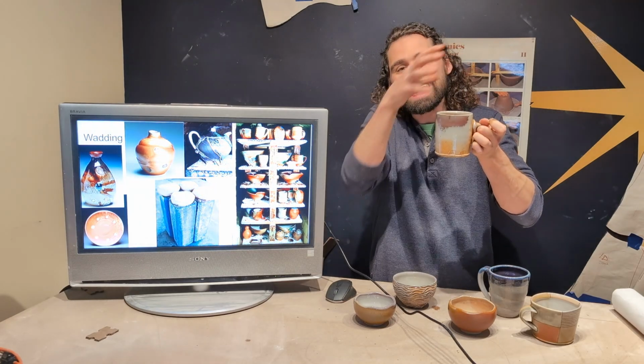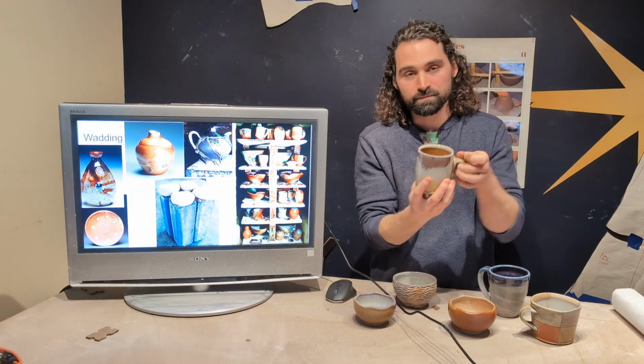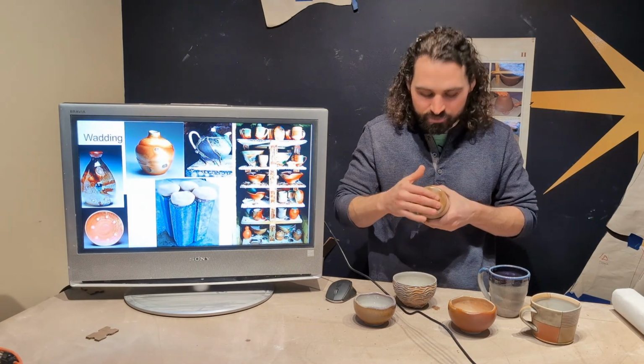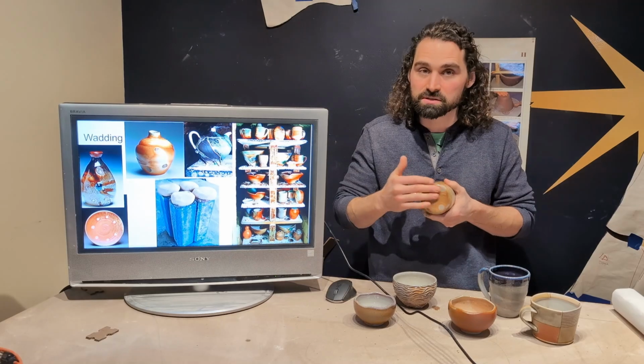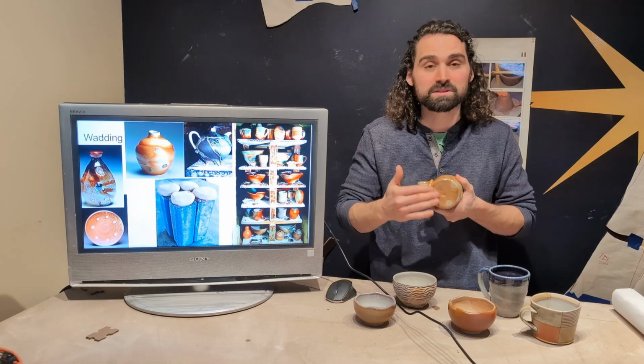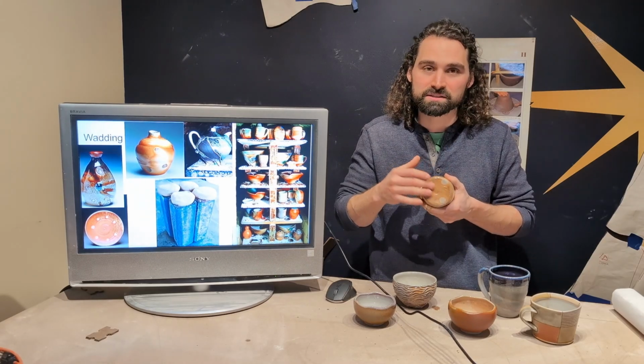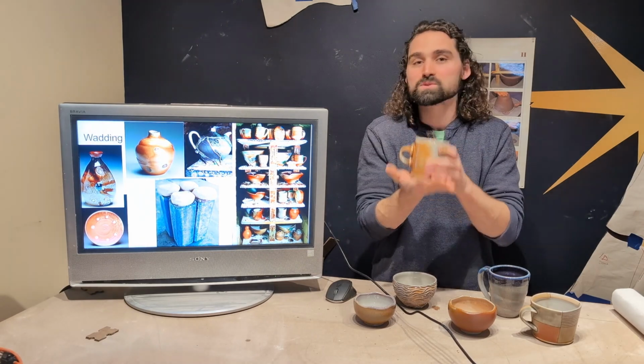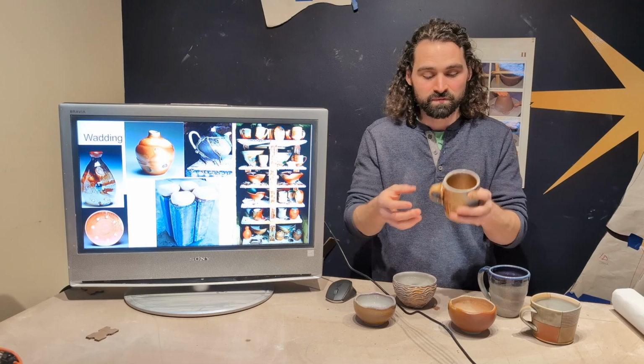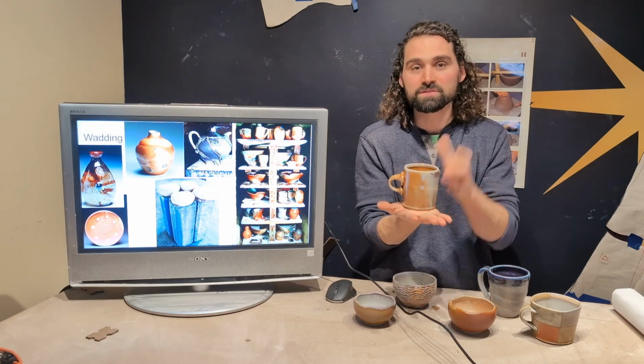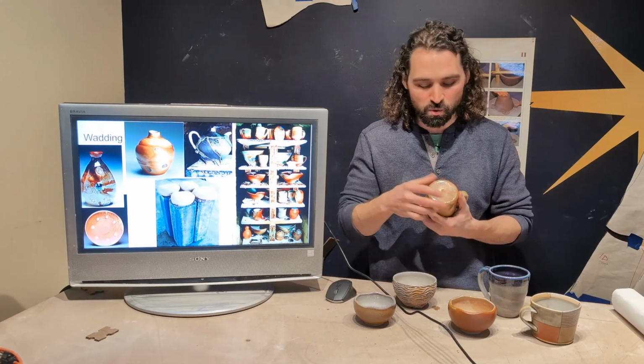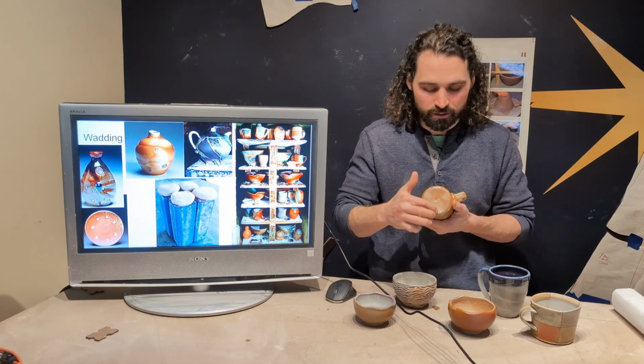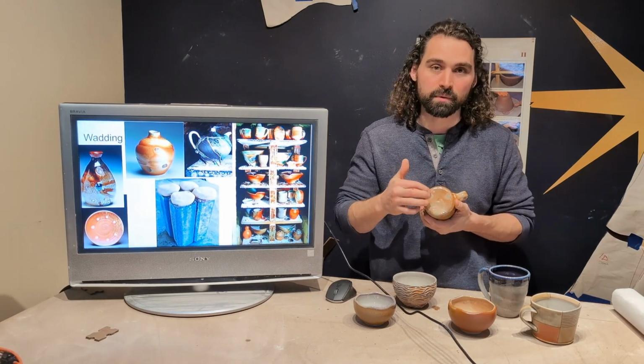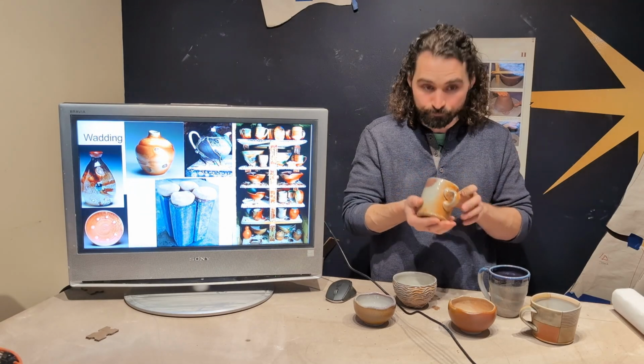That happens everywhere in that kiln. It will happen on the bottom of your pieces. This piece isn't glazed, it's just that sodium has gotten into the bottom of this piece and created this glossy surface. So your pieces, wherever they are, will stick. If you have them just on the kiln shelf, they will stick to the kiln shelf. So what we have to do is add wads to the bottom of these pieces to lift them up.